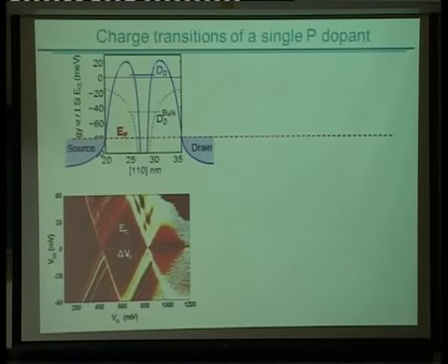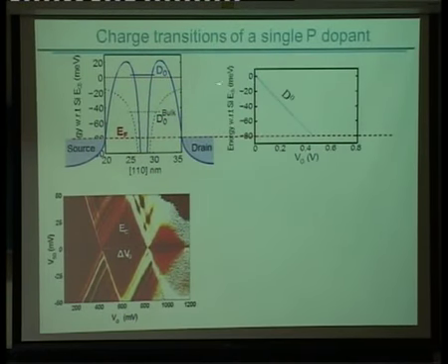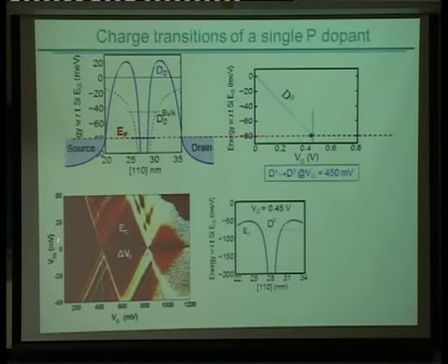And so we actually worked with him to try and figure out what happens as you apply a gate bias to this D0 state. And you can see as you apply the gate bias here, down the bottom, you can see this D0 state moving down until it crosses the Fermi energy. And that is the point at which you would get the occupation of the first electron on the donor. And it matches beautifully with the experimental results.